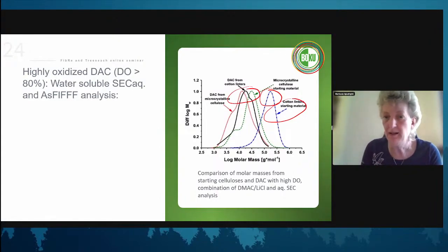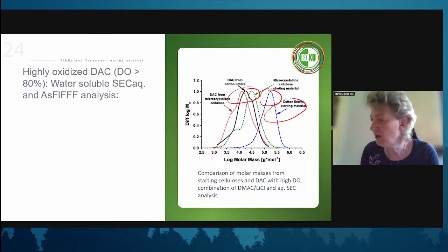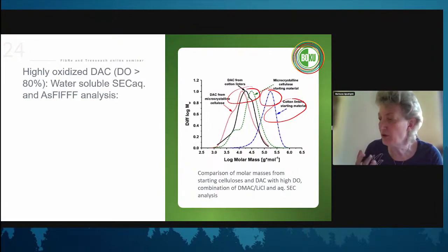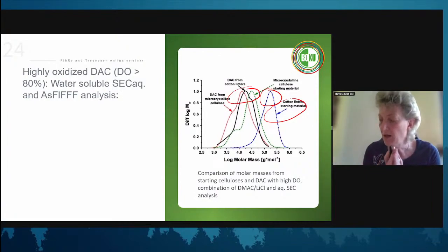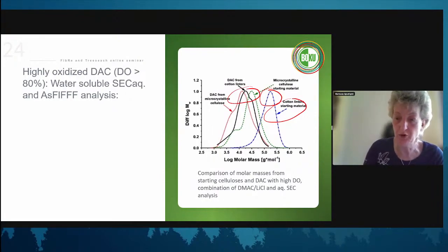These measurements are done in water, in an aqueous SEC, and we see the shift in molar mass. We have to say that those aqueous solutions of DAC are not super stable. If you measure those SECs in 3 different weeks, there's a lot of aging involved here. You probably get a lot of dynamics, a lot of opening and closing of crosslinks. So it's not a very reproducible material.